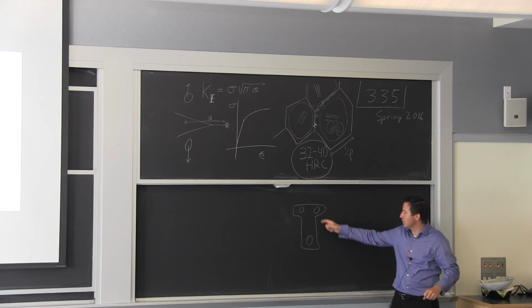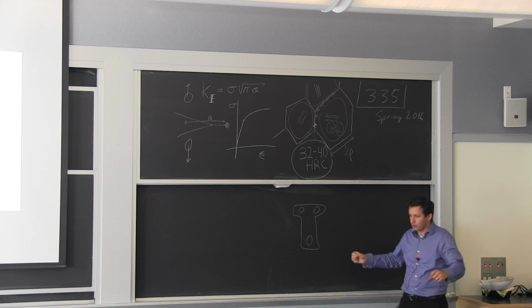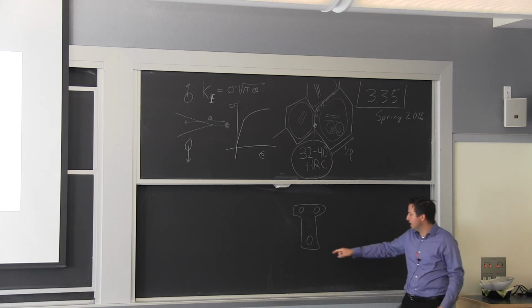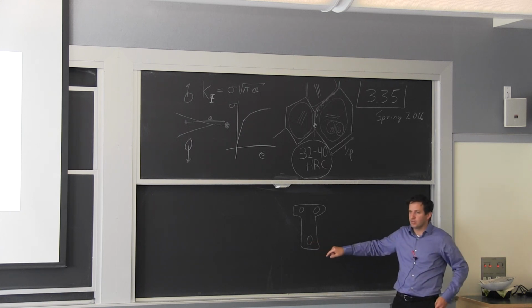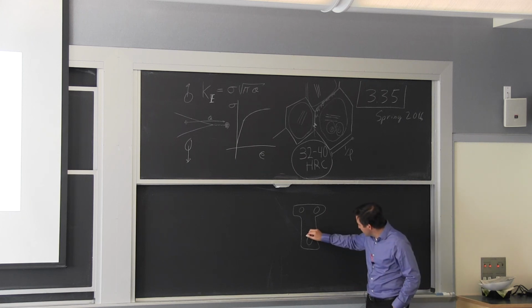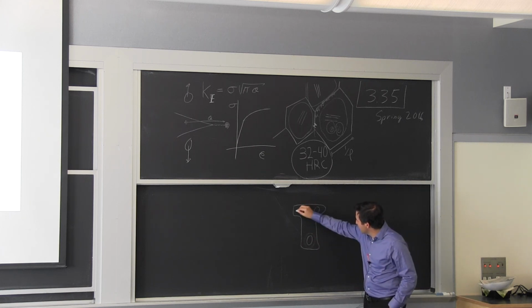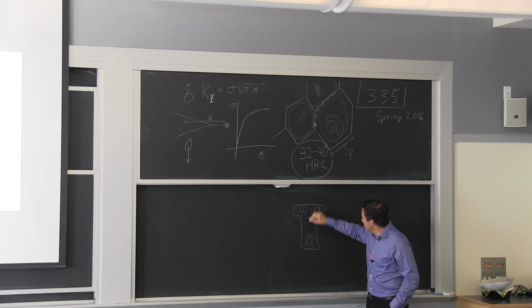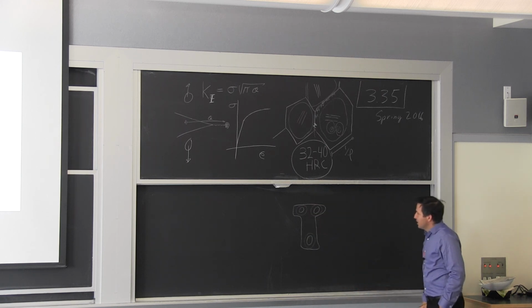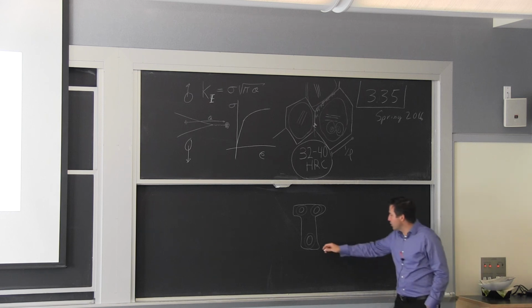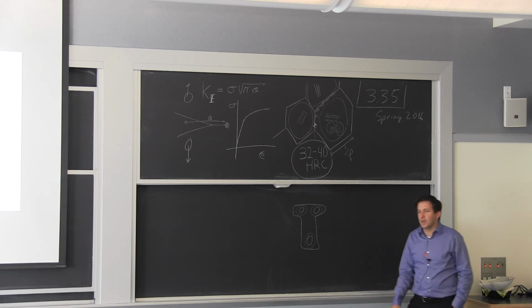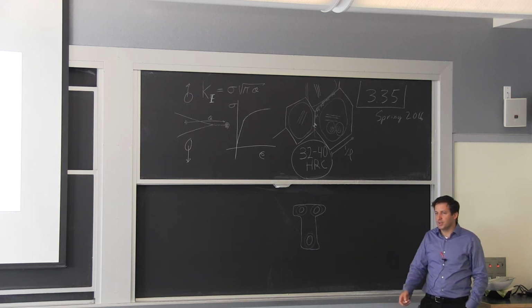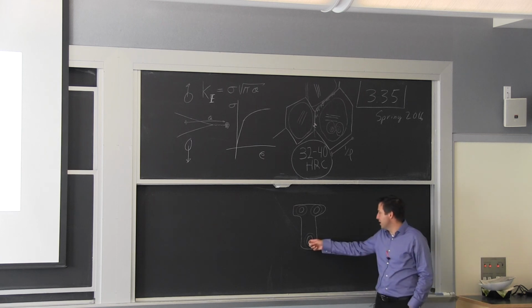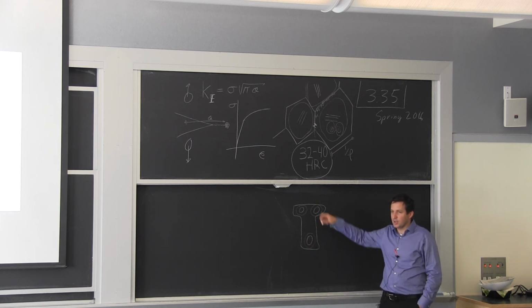When it's all cured, when the cement or concrete is all cured, you let it go. And you keep that steel in very, very high tension. But a lot of times they'll put a special grout around these strands. Or, depending on the system, you really try to prevent the environment from getting there and starting to break down your protection. Otherwise, you have parking garage repairs all the time when it wasn't done correctly. You save money. You use a small amount of steel and a large amount of concrete.